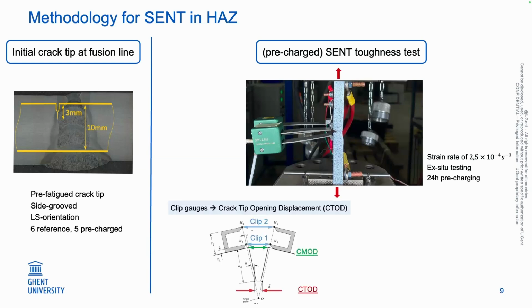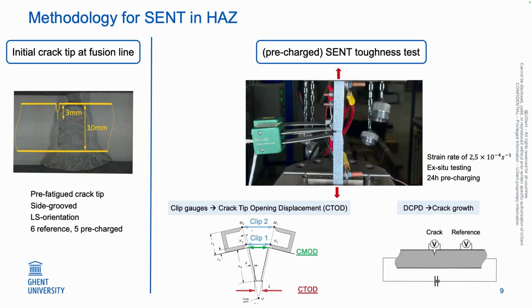During the test itself, we use clip gauges at different heights to, in the end, calculate the crack tip opening displacement of the test. And we also use DCPD. So we apply a constant current on the specimen, and we measure the voltage away from the crack and also over the crack. That's where we can then retrieve the crack growth during the test.